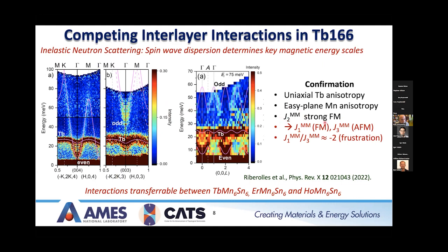J2 is strongly ferromagnetic. We have the easy plane manganese anisotropy. We find though that J1 is ferromagnetic and J3 is anti-ferromagnetic, and that gives us basically where these odd and even branches sit, and these patterns of what energies they sit at. And then J1 over J3 is about equal to -2, which indicates some frustration. What's important is we found that these interactions can be transferable. It's also been shown that the interactions that we solve for here can be transferable across the series for a number of these rare earths.